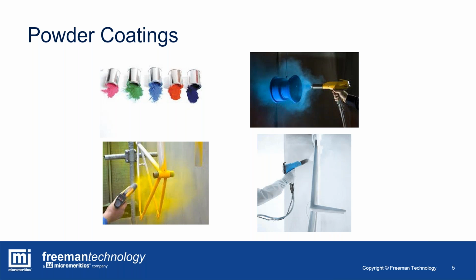and attracted to an electrically charged or a static process, whereby the metal surface has a charge that attracts the particles, and hopefully a uniform coating is achieved before that's then heated to form a permanent cover on that surface. And of course, cohesion and fluidization behavior are important attributes. If the material is too cohesive or agglomerated, then the surface finish may be compromised.